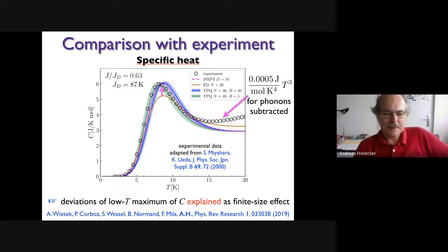Okay, now I'm going back here to the old experimental data. Here are the old experiments, so the circles are the old experiments. The orange curve corresponds to the old exact diagonalization data, and the ratio is basically the ratio that was determined before. We have readjusted the overall scale. And what you see is that with the new methods, we get basically a perfect fit of the specific heat here, without any further adjustable parameters.